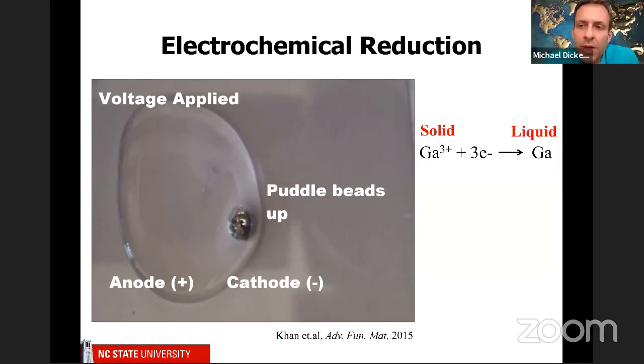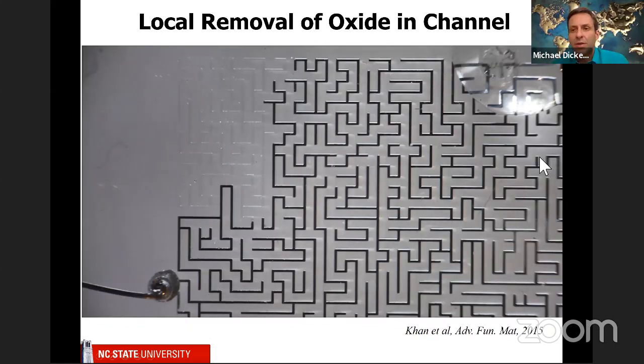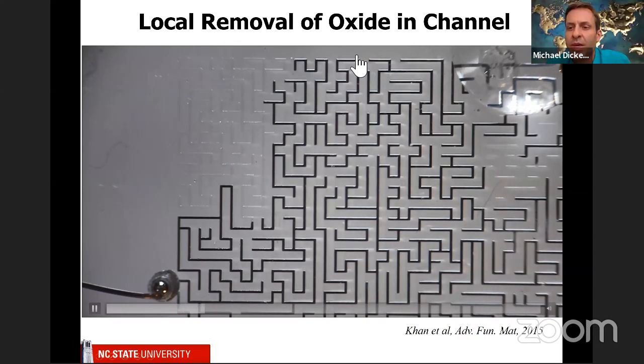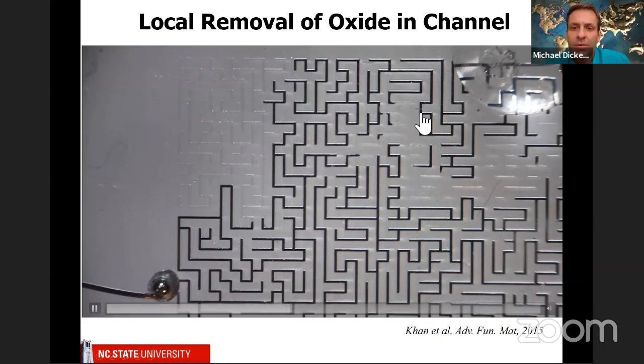So the beautiful thing here is that you can use voltage to turn on and off capillary behavior. And this is simply by a reduction reaction. You're inserting electrons into the metal. It causes the oxide to convert back into gallium. Okay, so what is this good for? Well, we showed just kind of a cute thing. We put liquid metal in a maze. We put a little droplet of water, electrolyte over here, and there's a droplet of metal over here.